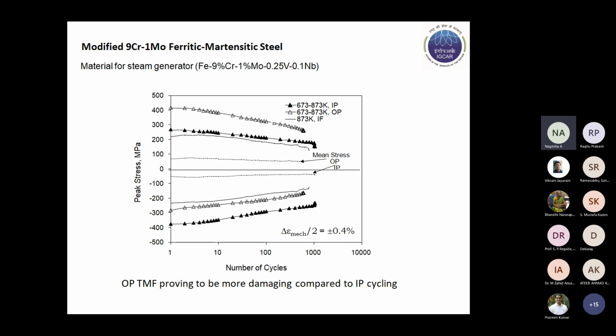Now, when it is exposed to high temperature, all these factors change. The precipitates have a tendency to grow, and this leads to restructuring of the martensitic laths. The lath structure undergoes change. It gets structured into a kind of cellular structure, and the breakdown of the laths leads to a reduction in strength, and the dislocation density also continuously comes down. All these factors lead to a reduction in the strength of the material.